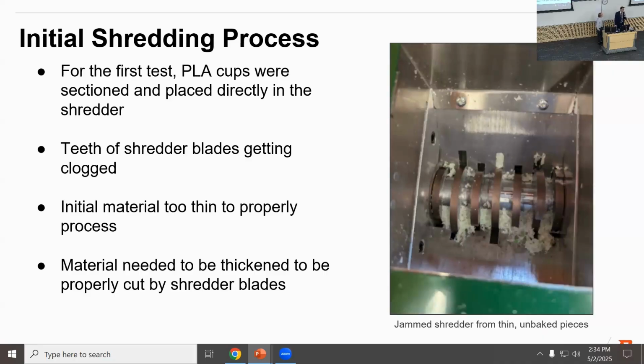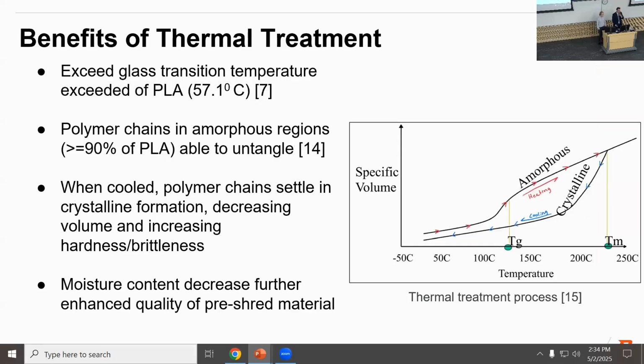So initially, we tried getting these section cups and placing them directly within the Filabot reclaimer, which was the shredder that we used. Unfortunately, what we found was that the plastic cups were way too flexible and thin and just sort of gummed up around the teeth of the shredder and didn't process properly. So we knew that going forward, we would need to somehow treat this material to either embrittle it or harden it or just make it more able to be cut properly by the teeth. So we decided to research the benefits of thermally treating it.